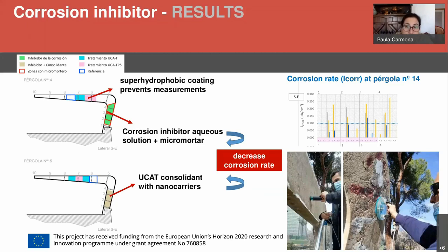In pergola 14, the one in the upper part of the slide, we applied the inhibitor in aqua solution, and after that we applied the micromortar. In pergola 15 it is different. We applied the corrosion inhibitor inside nanoparticles that were inside the UCAT consolidant.